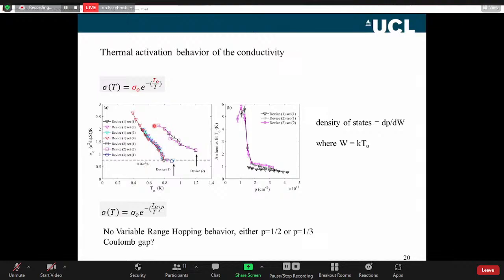The second device comes down, doesn't quite reach that minimum metallic state, but then goes very, very resistant. At this point, device 1 comes down to this minimum metallic state and then goes very resistant. So really what's going on, if you plot out now T0, that's T0 from the fit, from the temperature dependence of conductivity.